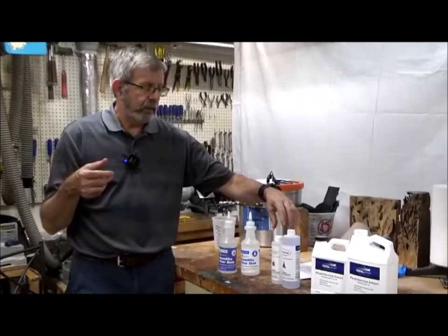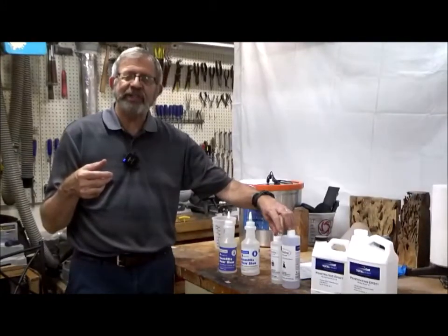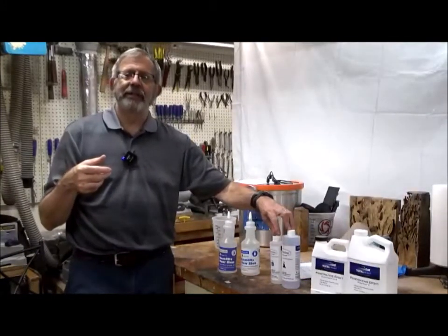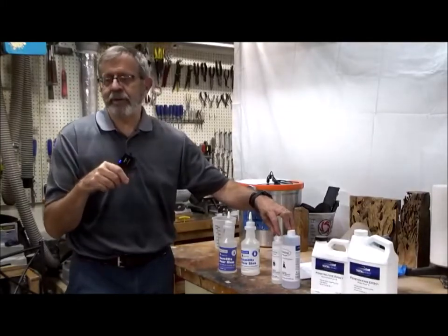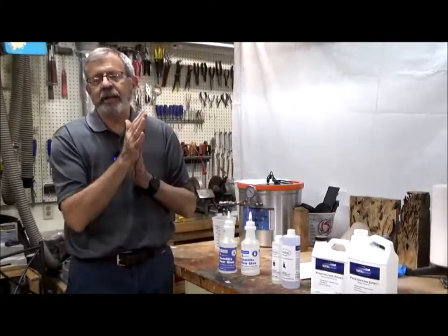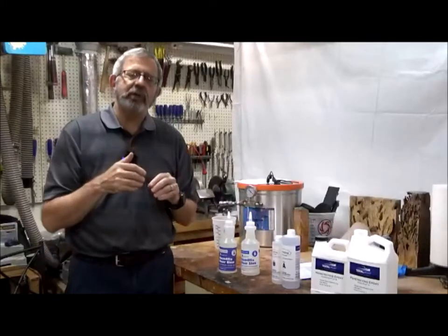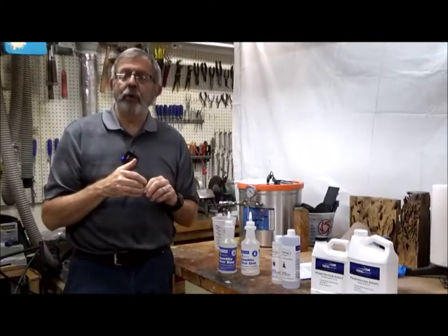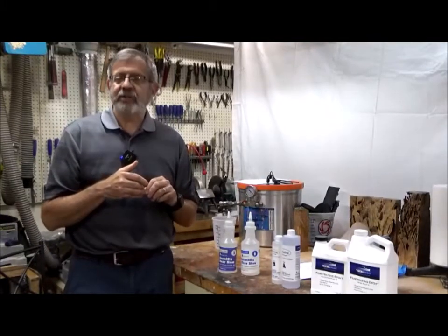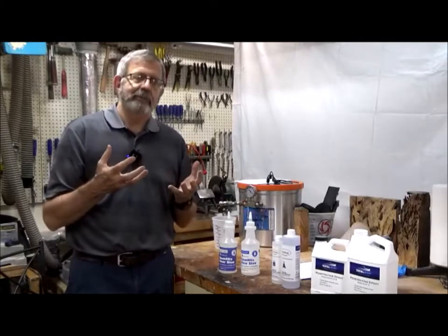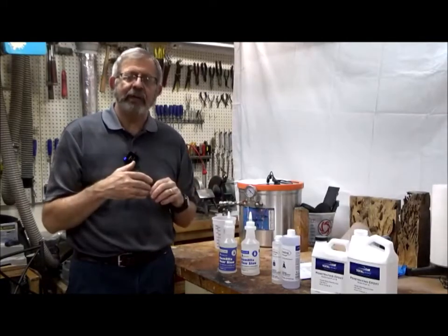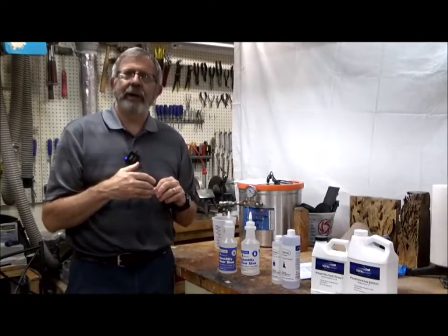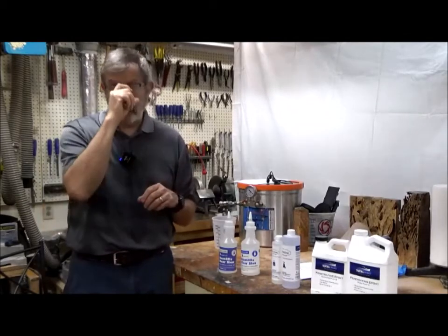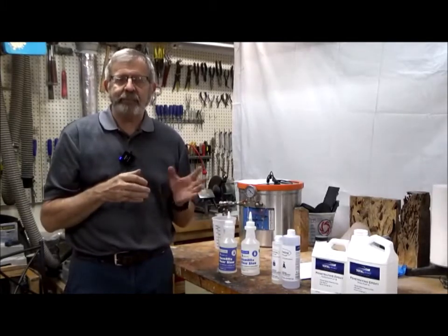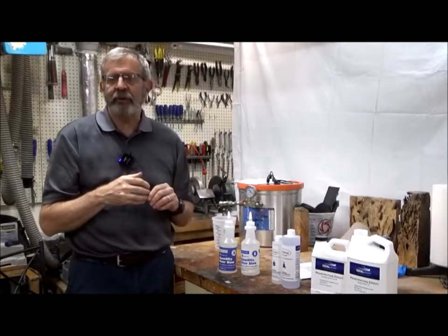It was still tacky at 48 hours. So in the pot that I mixed it up in, I just kept checking it, and it took over 2 days for it to set up to the point where I'd even consider it set. But it was probably 5 days before it was fully cured. And that's about what they say, is that give it a week before you turn it.